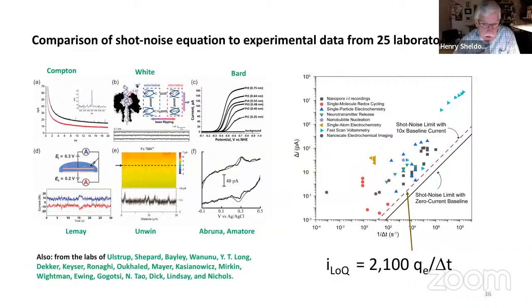Well, you can make the electrodes so small that you don't see anything. The arrival time of a particle to a 10, say a 10 nanometer size electrode, you may only get one per hour. And that's a poorly designed experiment. So you would use a 10 micron size electrode, and then the frequency of arrival is higher, and you can see a train of pulses like you see here from this experiment from Richard's lab. Okay, impurities, it's the same.